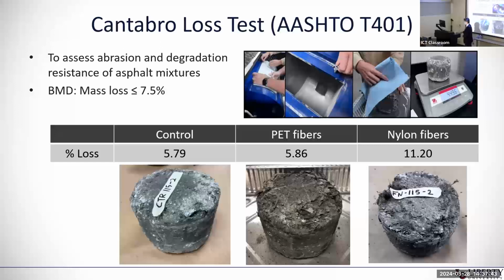Balanced mix design in Virginia has a specific criterion: this material loss should be less than 7.5%. So the nylon fiber is out in terms of this spec, but we used only 0.4% nylon content for these nylon fibers.